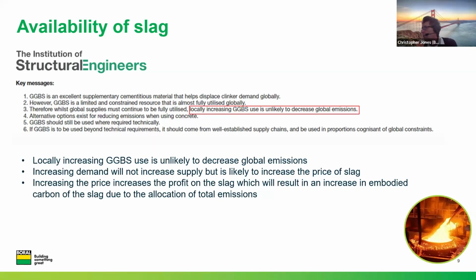Locally increasing GGBS use is unlikely to decrease global emissions. The production of slag will not increase simply because there is an increase in demand. An increase in demand for a fixed supply will only increase the price of the slag so that the demand and supply are balanced. And to make it worse, due to economic allocation that I mentioned earlier, a greater amount of emissions from the production of the iron will be attributed to the slag. This will reduce the reported embodied carbon of the steel, but if you're only interested in low carbon concrete, that doesn't help much.